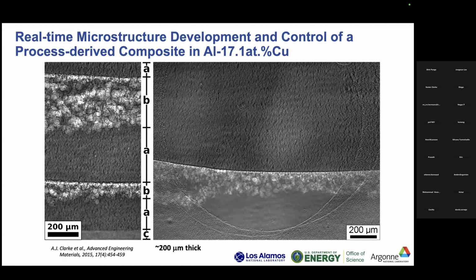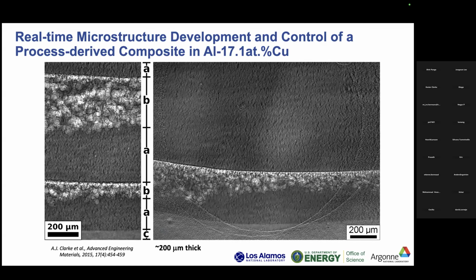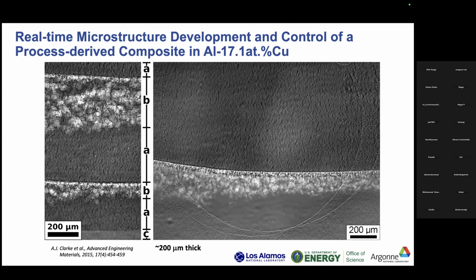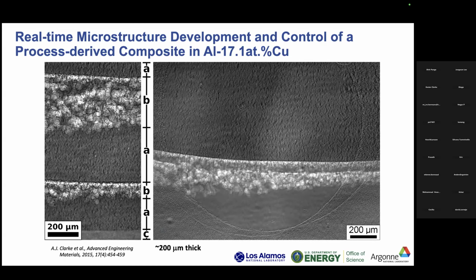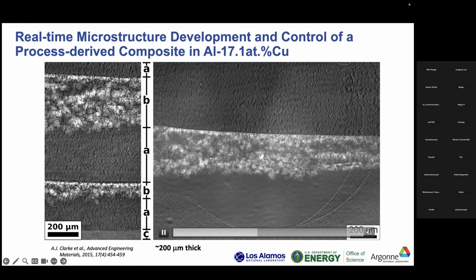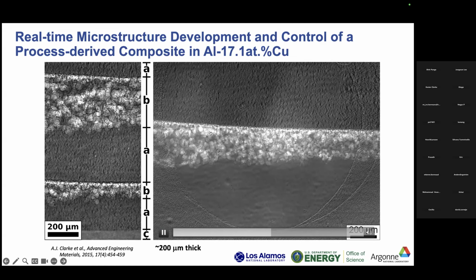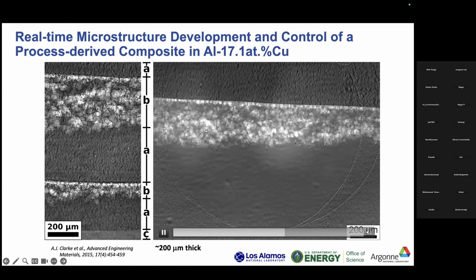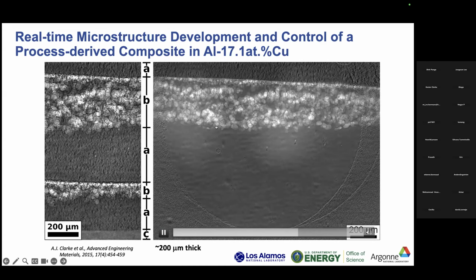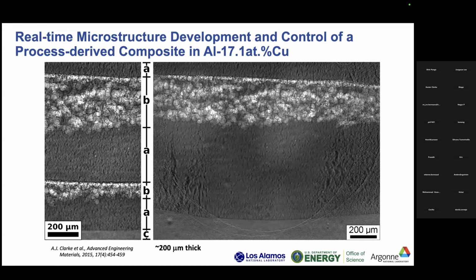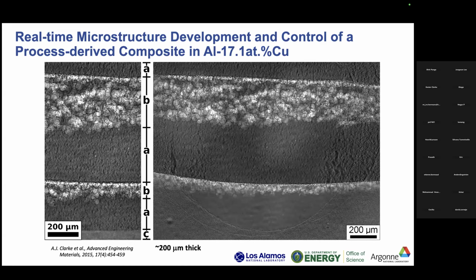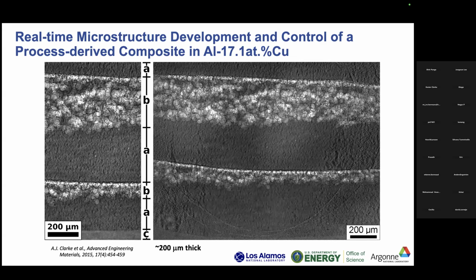And here in the previous example, you kind of saw the eutectic break up into those matchstick bright aluminum-rich fragments. Here you actually see those aluminum-rich fragments are sort of spheroidized and coarsening. And the aluminum-rich phase is lower density. It's buoyant, so it actually floats at the solid-liquid interface. And then as we move forward, we trap in that layer and then sort of wash, rinse, repeat. We create another layer and create this artificial composite kind of microstructure.